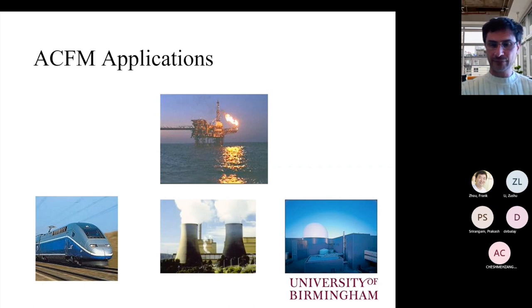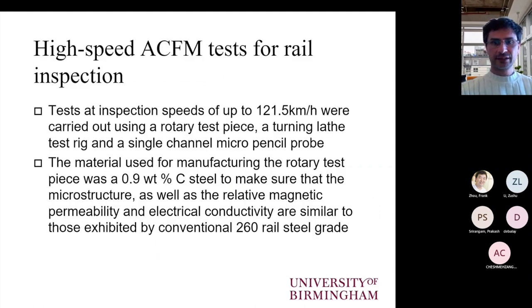When, of course, the instrument is available, because MPI is a more readily available technique, even though it doesn't offer the same sensitivity as ACFM. With ACFM, we have conducted a number of experiments as part of an EPSRC project, as well as a European project a few years back. So we did tests in Birmingham up to 121.5 kilometers an hour with a special rotary test piece. So in this case, to achieve the speed, we used the turning lathe on a sample that we had specially prepared with spark eroded defects of 2 and 4 millimeter slots deep.